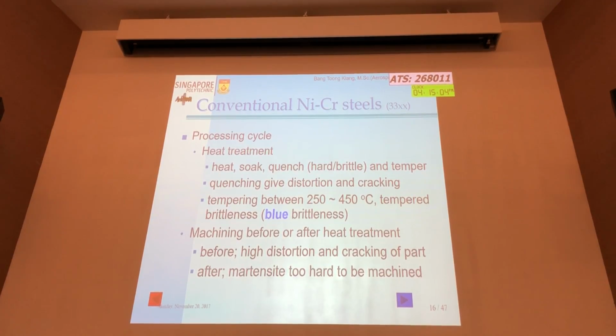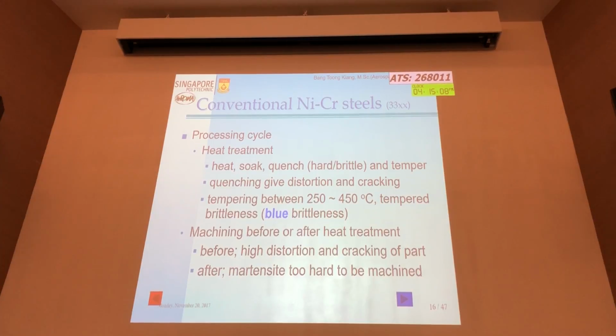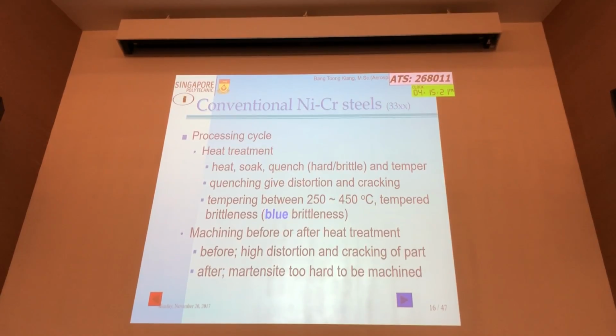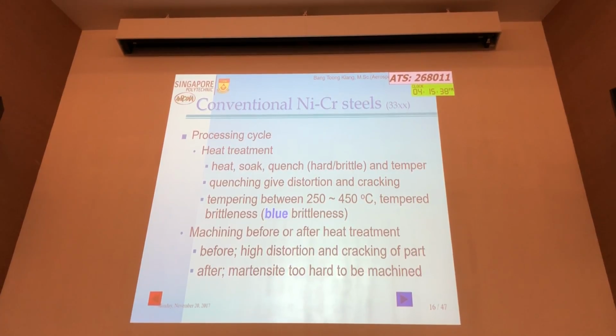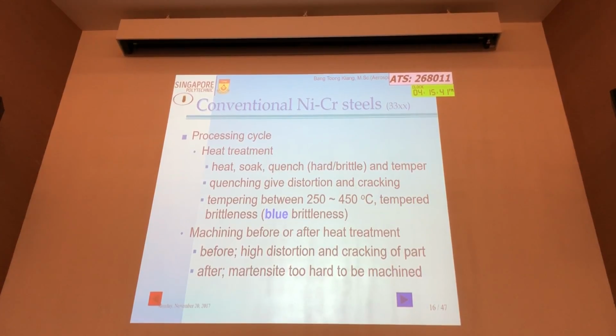If you look at the one you studied, if we temper it at less than 200, 250, you will merely reduce the residual stress without affecting the toughness. Still strong but not very tough. So usually we do it above around 400 to get a good combination of toughness. If you do it at more than 600, you will lose all the strength and gain the toughness. So you do it at 200, 400, 600. That is normal. And you get the combination.